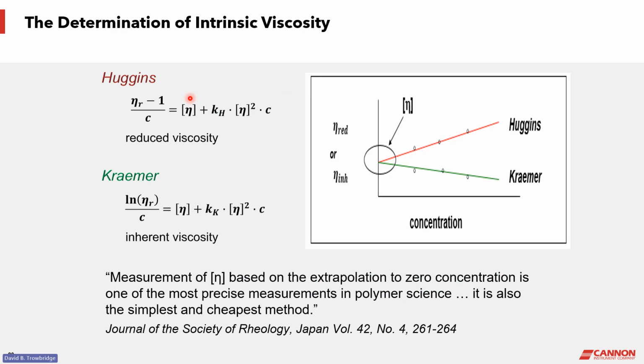In practice, often we combine that with a Kramer equation, which operates the same way as the Huggins. You can extrapolate to 0 concentration and isolate the intrinsic viscosity in a separate term that can be equated to the log of the reduced viscosity over concentration. So you can combine both of these equations in a dual extrapolation on the same plot and get a common y-intercept that represents the intrinsic viscosity.